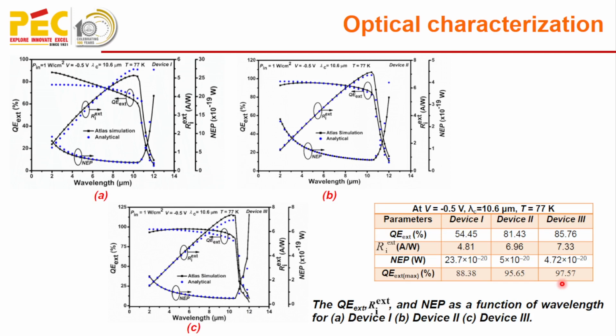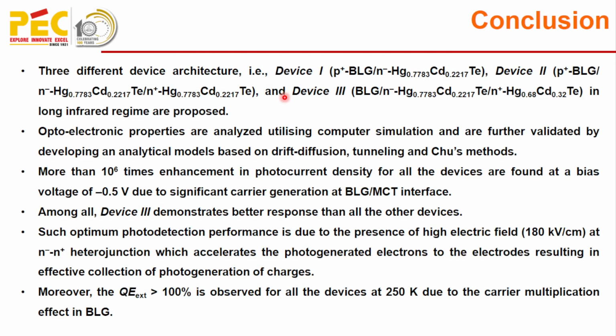It was found that more than 10 to the power 6 times enhancement in photocurrent density was observed for all the devices at a reverse bias of minus 0.5 volt, which is due to the carrier generation at the bilayer graphene and mercury cadmium telluride interface. Among all, device 3 shows better performance as compared to device 1 and device 2. This optimum performance is due to the presence of a high electric field, which was 180 kilovolt per centimeter at the N negative and N positive heterojunction, which accelerates the photogenerated electrons to the electrodes, resulting in effective collection of the photogenerated charge carriers.